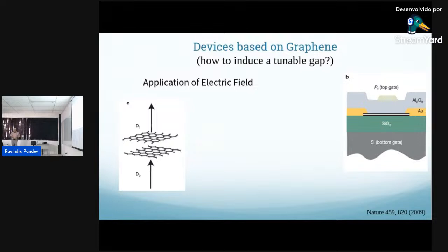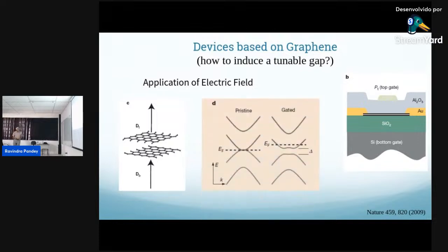So they made this device. This is again typical bottom gate. It's dielectric material. You apply layer graphene and top gate, apply the electric field. And what you can see here, this is without the electric field. You have the zero gap, but once you apply the gate field, it sort of induces a gap. But again, go to the electrical engineer, they said yeah, concept-wise it's good, but it's not easy to make